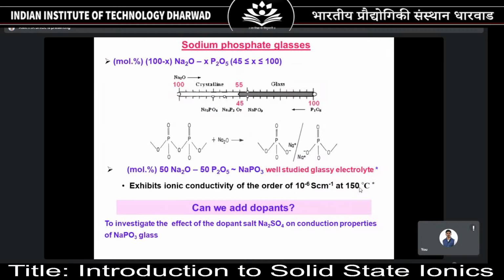So this is how you can have control over the composition. We have glass former P2O5, which is 100%, and sodium oxide here, and we keep on adding the content of sodium oxide as a modifier into the phosphate. You cannot keep on changing it indefinitely; only up to 55% of sodium oxide and 45% of phosphorus pentoxide can you attain glass.